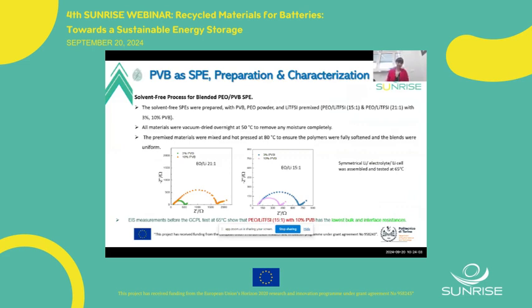And at the end, I'll show the results regarding PVB as a solid polymer electrolyte. We used a solvent-free process that is promising and good for making the solid polymer electrolyte membrane. In this case, we mixed PEO-PVB with lithium salt, with ratios of PEO to lithium salt of 15:1 and 21:1, with different percentages of PVB, 3% and 10%.